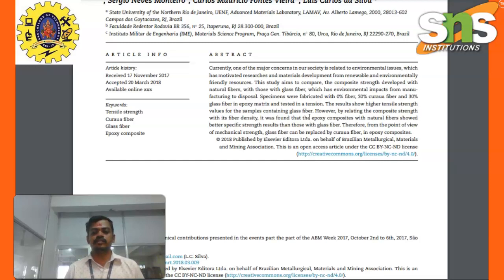in tension. The result shows a higher tensile strength value for the sample containing the glass fiber. However, by relating the composite strength to density, better specific strength results were obtained for those with curaua fibers. Therefore, from the point of view of mechanical strength, the glass fiber can be replaced by curaua fibers in epoxy composites.